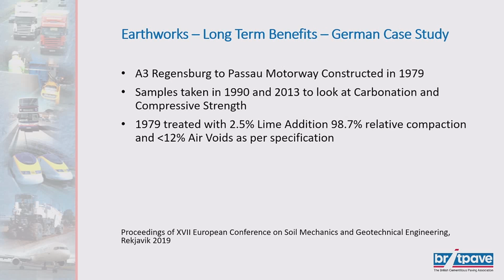So just going to have a look here in terms of a treated soil, in terms of long-term benefits. This is an example from a European conference from 2019 of a road that was built in Germany in 1979. They took samples in 1990 and 2013 to look at carbonation, and then compressive strength. It was initially treated to the German specification, which was 2.5% lime addition, 98.7% relative compaction. I think they had to achieve 98, and below 12% air voids.